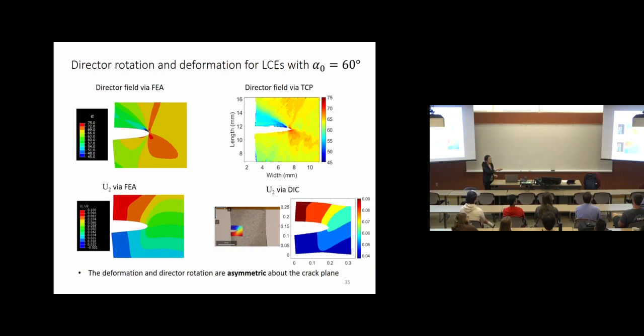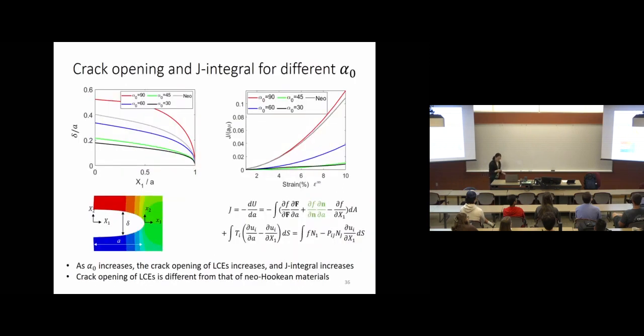So you see the displacement field is highly anisotropic with respect to the crack plane. Finally, I'm also showing you the crack opening plotted on the left-hand side for the different initial director angle and comparing with a neo-Hookean material. As you can see, they are very different.